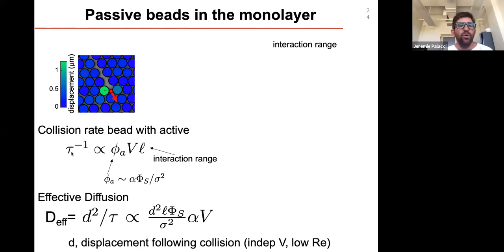So we can compute the collision rate. From that, we can compute the effective diffusivity. The effective diffusivity is going to be the typical displacement following a collision squared times the collision rate. And there's one feature about the displacement. Because we're at low Reynolds number, we don't expect the displacement following collision to depend on the speed of the active particles.